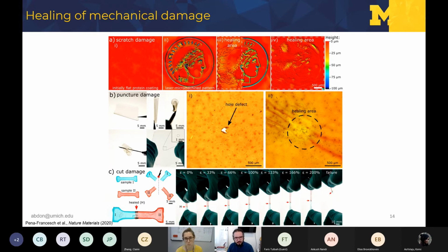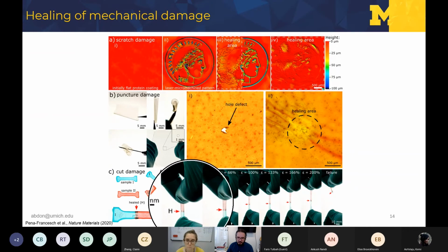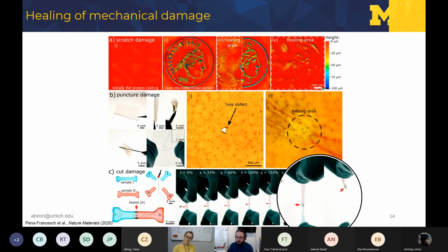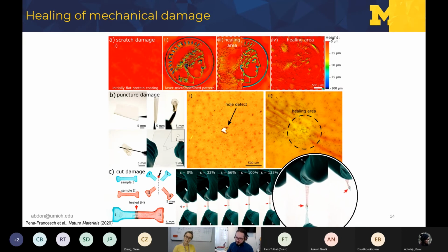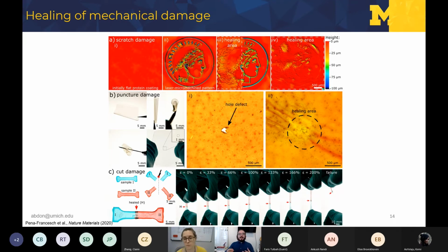We tested these against puncture damage. I think these were like 20 micron flexible protein films that we stabbed with many different needles, and you can see how you can repair these small scale hole defects. But we also looked at how the material recovers from complete cut damage into different pieces. What we're very excited about is that this is the area that was the healed area, and when this breaks, it breaks from a different position, which is telling us that the healing and the network repair is effective, and that the healed area is at least as strong as the original material, which is great, because it's telling us that this works, right?